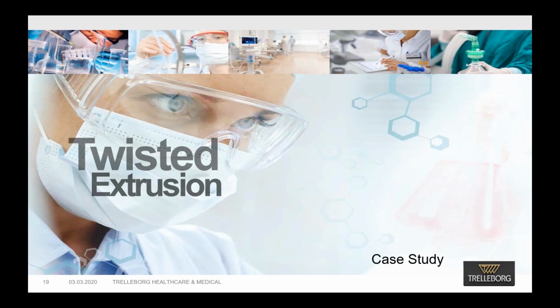The twisting lumen create longer wire lengths in bend locations to distribute the dynamic bend loading more evenly across the conductor. This is in comparison to non-twisted tube, for which the conductor on the outer radius of the bend sees higher loads and is more likely to fail over the millions of bend cycles that occur during the life of the implant.